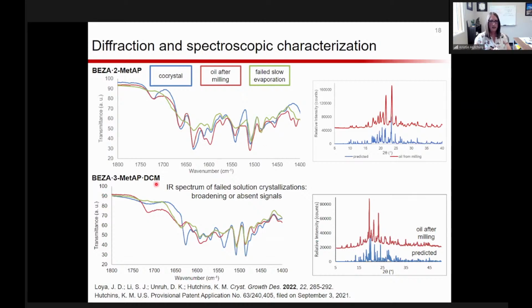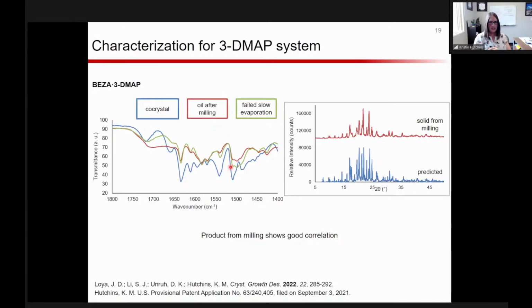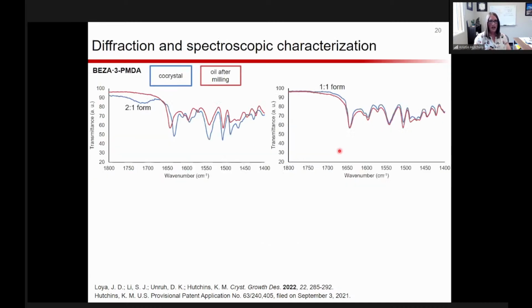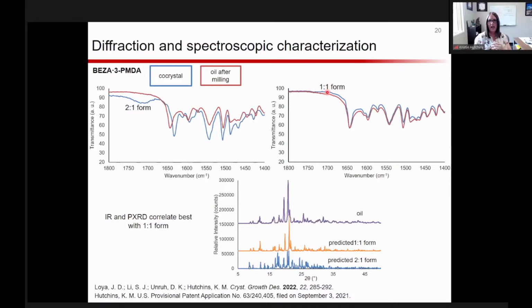In the case of the 3-dimethylaminopyridine, that crystallization included dichloromethane. When we look at the IR spectrum, what we see is surprising for us. And so it got us questioning why it's failing when the milling and the co-crystal look really similar. And again, by powder X-ray diffraction, that product shows really nice correlation. But then lastly, what I want to highlight is this odd case with this new 1-to-1 form. And you can see the IR spectrum of the oil after milling matches incredibly well. And the powder X-ray diffraction also shows really good correlation to that 1-to-1 form.